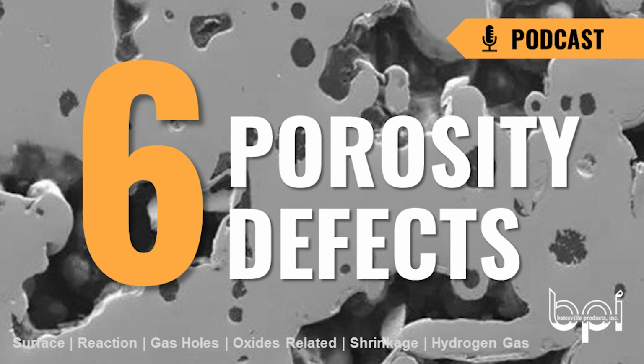That oxide was actually generated in the furnace or the melting furnace, so it's not just a result of your gating. It can be entrained in your melt. If you're using a lot of scrap, and particularly if you're remelting gating, because gating will have oxides on it, you can introduce those oxides right into the melt, and they're going to stay in there unless you have some way to filter them out. If you're making an alloy addition, you have to make sure that you get it plunged and thoroughly distributed through the melt. The oxygen not only attaches to the aluminum to form the aluminum oxides, it will combine with the magnesium to create a magnesium oxide.